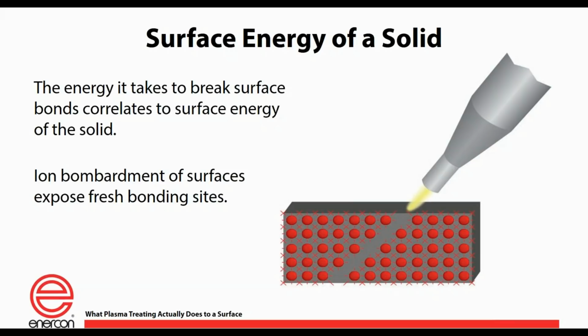So I'm just breaking the bonds between those molecules. If I'm trying to cut a block of aluminum, that's going to take a lot of energy. The more energy it takes to break those bonds, the higher the surface energy of the material is. So metals typically have a higher surface energy than plastics or films, and that's because it takes more energy to break those bonds. Now, if you introduce plasma to a surface, you see the bonding sites there where we're going to start to affect your surface energy.